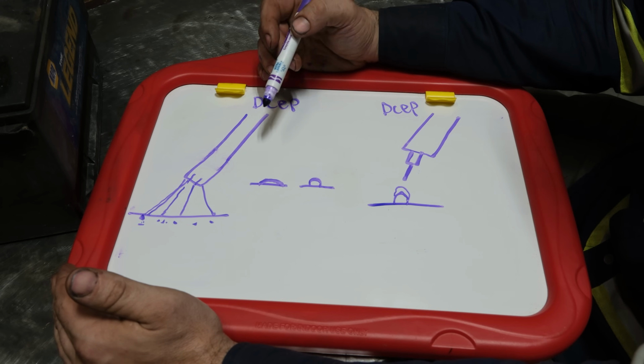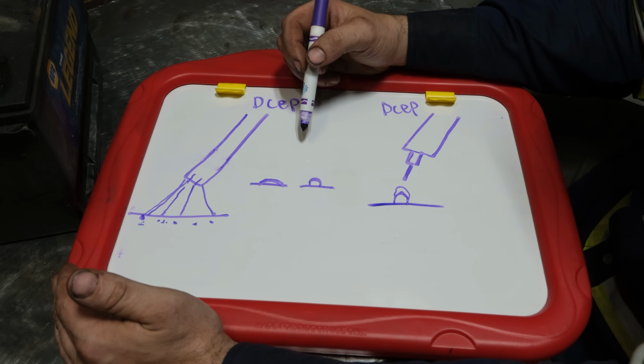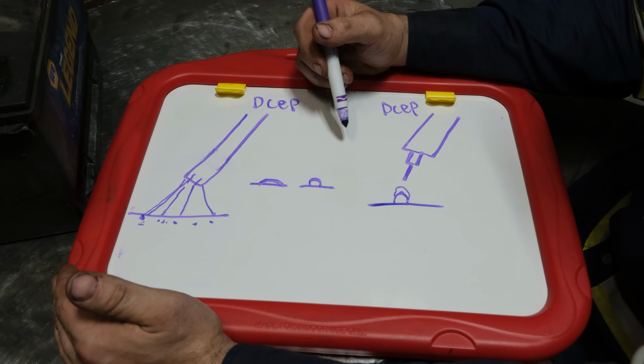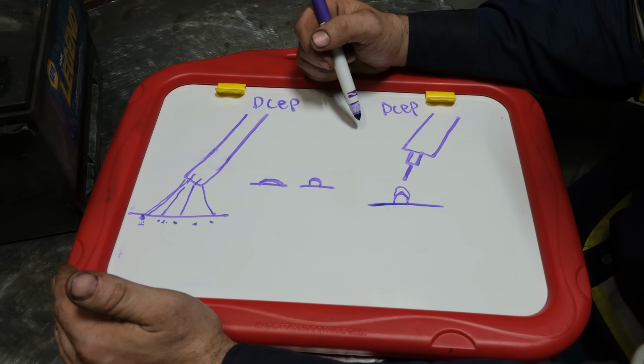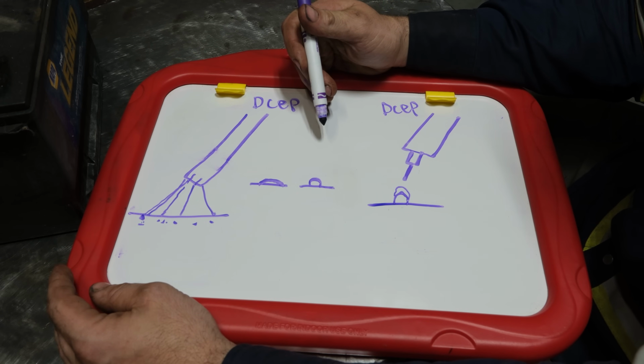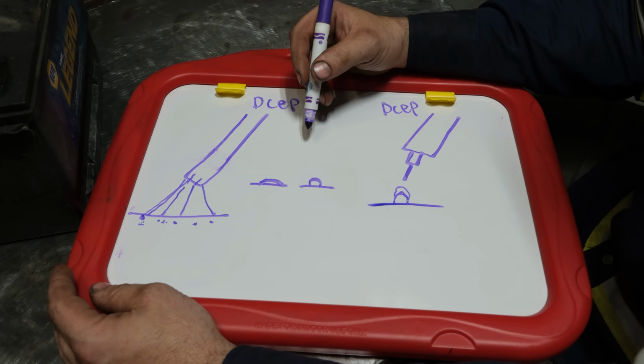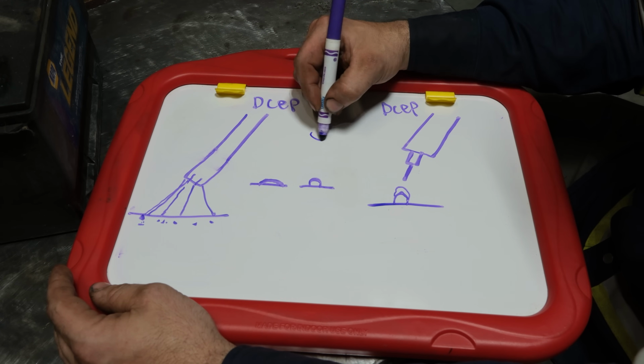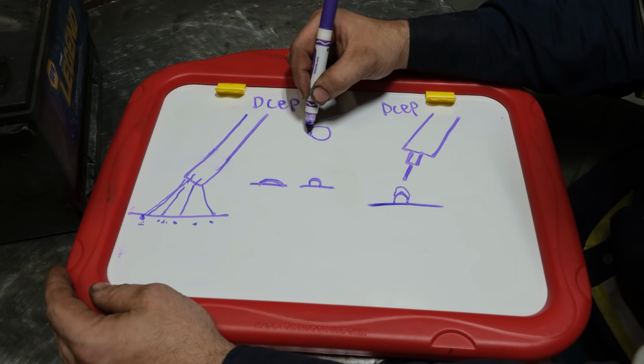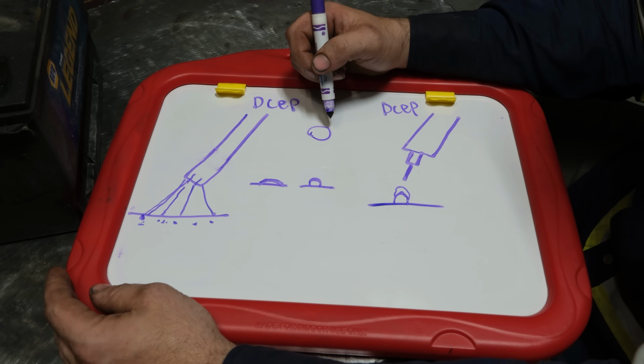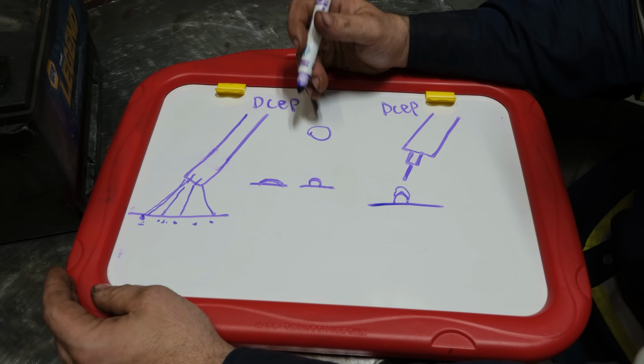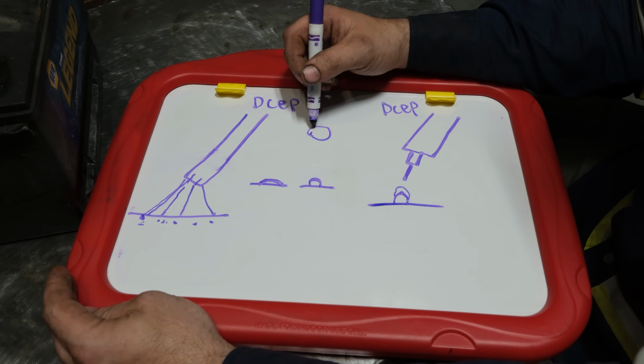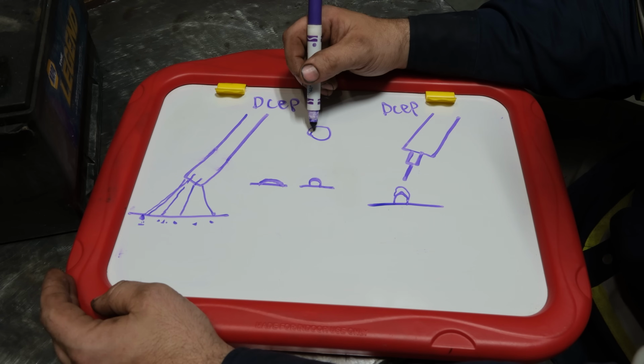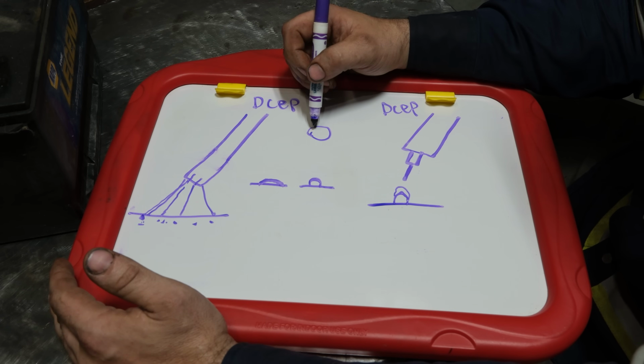Now, the interesting thing is self-shielded flux core wire runs DCEN just like TIG. And I think there's a couple reasons for that. So flux core wire is a very small hollow tube. The metal exists on the tube, on the outside, and the inside is filled with flux. Well, with self-shielded flux core, you don't typically run super high wire feed. You run fairly high voltage for that wire feed speed. And ultimately,